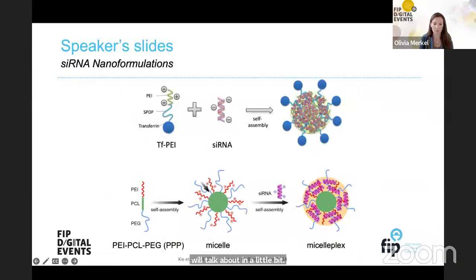bit. But before that, I wanted to give you a bit of an idea of some of the materials that I will mention later on in the presentation. We currently are working on new biodegradable materials that I hope will be published very soon. And I hope to give an update soon about some of the more exciting and most of all more biocompatible and biodegradable materials. But for a lot of the proof of concept work that we've done in the past years, we use polyethylenimine, PEI. And PEI is a very broadly used non-biodegradable material. We usually use low molecular weight PEI to reduce side effects and toxicity. And we actually saw that in healthy animals, PEI is tolerated quite well. But we don't use PEI as it is, but we usually modify PEI polymers, for example, with targeting ligands, such as transferrin, which you see here.